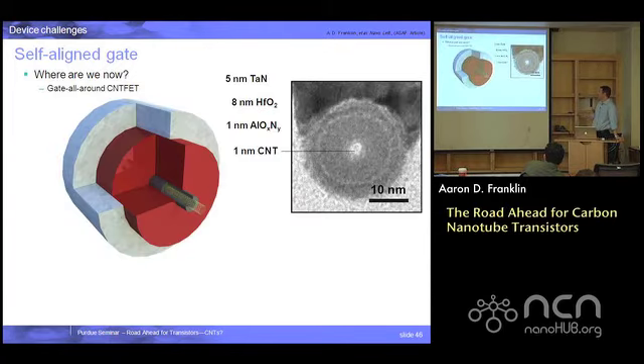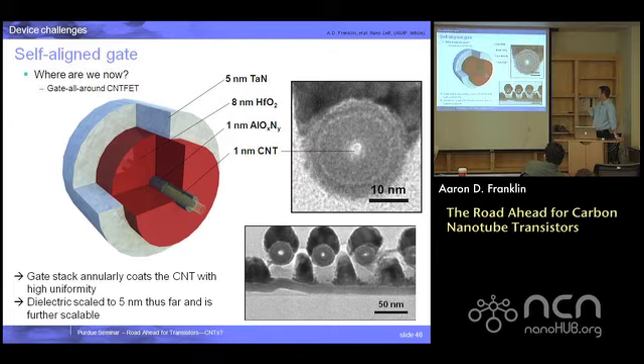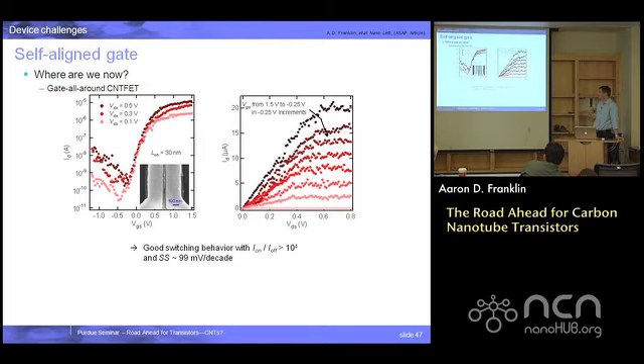Okay, and this is the pretty TEM image of that device showing the uniformity of the gate all around. So the nanotube is right in the center there, and then you have this adhesion layer of about a nanometer or less, followed by the gate stack, and then eventually a tantalum nitride gate metal so that it also encompasses the channel. This is just looking at that TEM at an array where you can see the uniformity on the different nanotubes. And here's the device results.